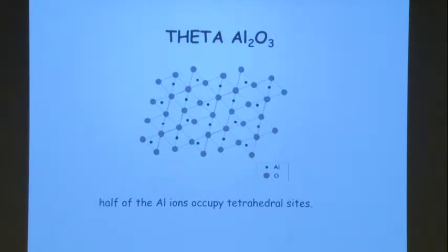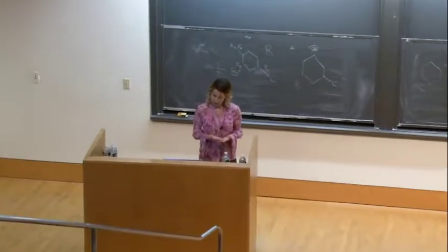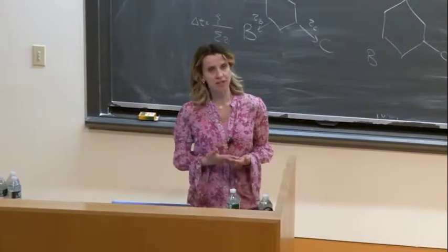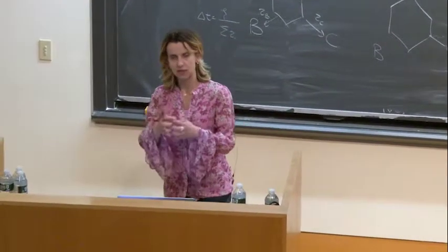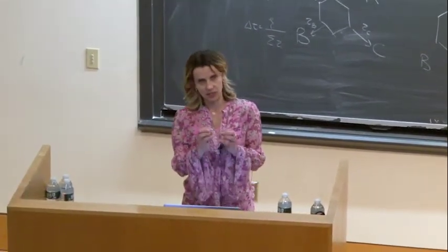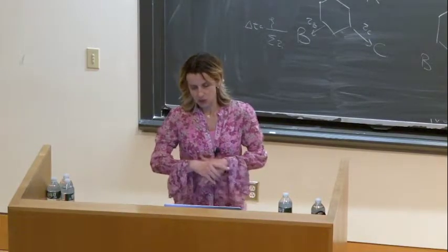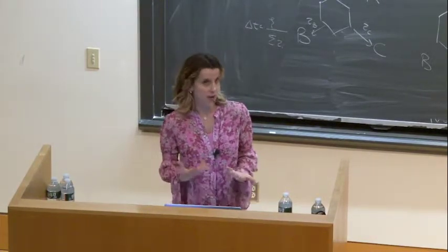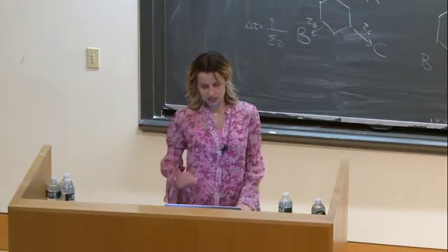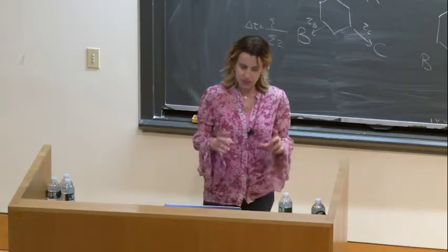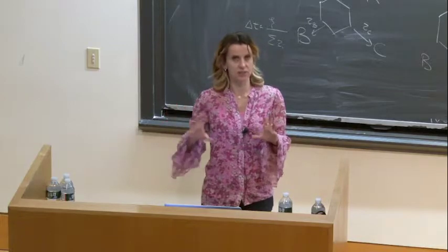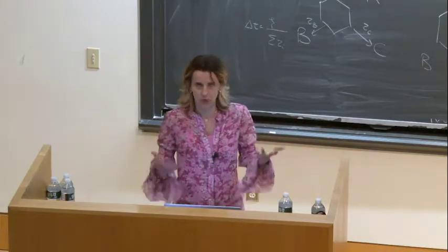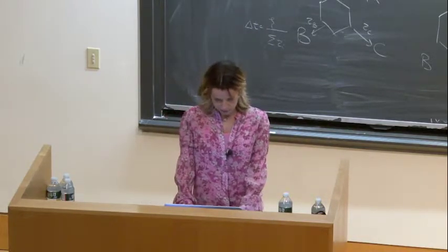So the question for us was, if I have nanoparticles of alumina, of alpha and theta, when they are put in a flame and they grow, for example, they get together, like the coalescence that I showed you before, what kind of phase do I get and why? So that we can control it. If I tell you that in this condition I form theta, for example, then change the condition if you want alpha, just to give you an example, or control the temperature.